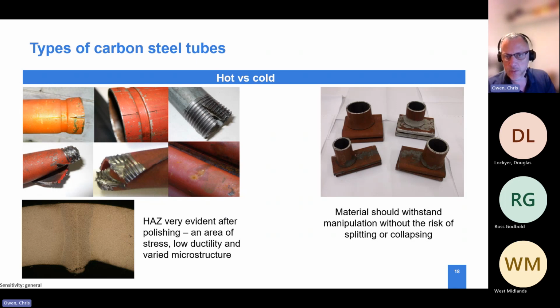So basically we take the tube and we try and force it apart, see whether it splits, and we flatten it both on the weld and 90 degrees off the weld to again see if we can initiate splits. Once we know that weld meets our requirements, then obviously it can go into the parent hollow and into what we call stretch reduction at Corby. And this allows us then to superheat that master tube and then elongate it to get all the different shapes and profiles we need to service our customer requirements.